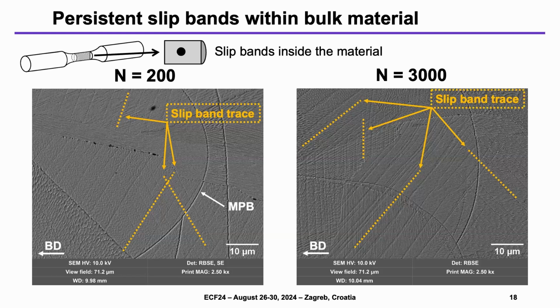And as you can see, also in the interior of the material there is the presence of some bands with different inclination. And in this case, we were also able to observe that some of the bands can overcome the so-called melt pool boundaries, which do not represent an effective barrier to slip localization. Of course, with increasing the number of cycles, in this case, the bands become wider, let's say. At this point, we also performed some TEM analysis, once again to describe the dislocation arrangement within the bands.